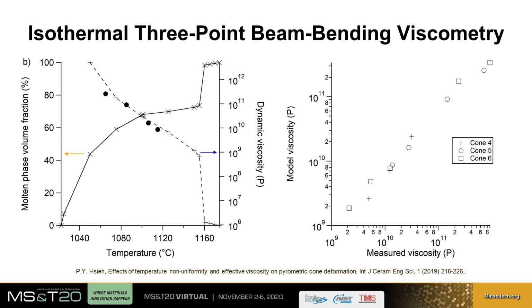What Thomson lacked at the time was access to thermophysical modeling software capable of computing the effective viscosity of these pyrometric cone compositions in a subliquidus state. Subsequent advances in computers made it possible to apply thermophysical modeling to a wide range of problems, including the estimation of effective viscosity for subliquidus silicate melts. The effective viscosity estimates found through thermophysical modeling were in excellent agreement with Thomson's experimentally measured viscosity values, lending support to the validity of the approach.